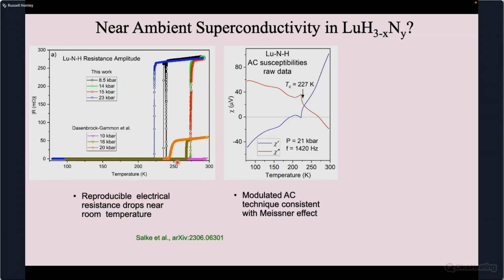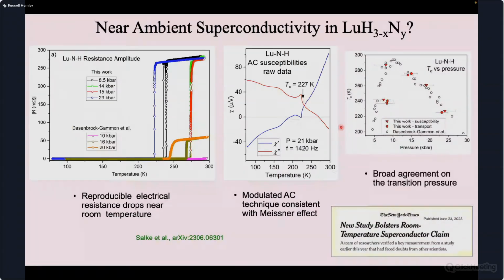We also followed up with magnetic susceptibility measurements, very much like what we pioneered for sulfur and other materials, showing the kind of signal you expect if you're at the onset of the transition in terms of the diamagnetism onset. And then if you plot the TCs, the resistance drops or the change in the susceptibility as a function of pressure, you get this dome, which very much matches what was seen in this report. And this generated quite a bit of excitement.